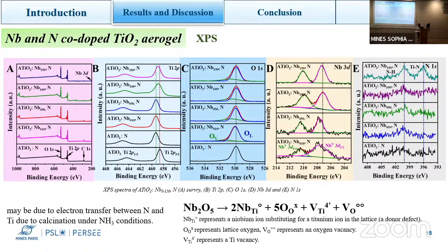Could be. It depends on the detector sensitivity. Maybe even just a little bit of change in electron density can shift the peak. But here, maybe also because of oxygen vacancies, the surface electronic structure is complicated to say.